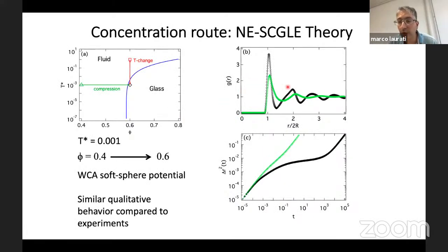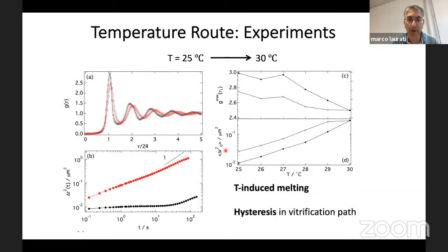And similar features were found in the theory by Magdaleno following, essentially, a similar compression route. Then we did the following experiment. Starting from the state that was reached through the concentration route, we increased the temperature to 30 degrees to reduce the packing fraction and therefore melt the system. And as you see, at 30 degrees the pair distribution function now moves to the right, and the peak becomes smaller, and the dynamics, of course, become much faster. They are not entirely diffusive, maybe, but almost diffusive.